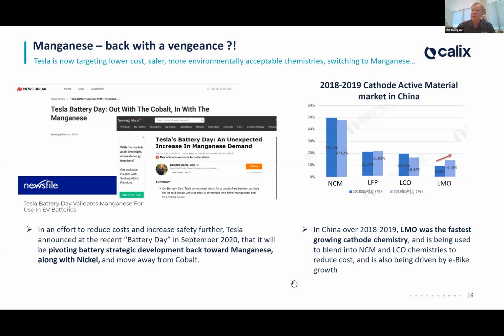They're looking at combinations with nickel to keep that sort of mileage and stability up. But interestingly, in China, on the graph on the right here, you can see that LMO, or the manganese, is in fact the fastest growing part of the market in China. And what's interesting there is they're using the LMO, the manganese-based chemistry, to blend into other chemistries. So they're using a combination of the other chemistries and the manganese to keep the costs down, but to keep the performance and stability up. And so manganese, which was shrinking away a little bit as a poor cousin, is actually firmly back on the table as a potential chemistry in this growing market.